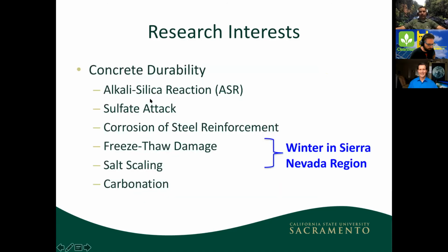There are other things that attack concrete. Freeze-thaw damage, again, this is in the Sierra Nevada region, where we have a lot of cycles of freezing and thawing. Basically, you have water penetrating inside of concrete, the temperature drops down, the water freezes, and it causes the concrete to start exploding from inside. Very similar to what would happen if you got a Coke bottle and stuck it in the freezer and left it overnight. That Coke bottle is going to explode as the Coke freezes.